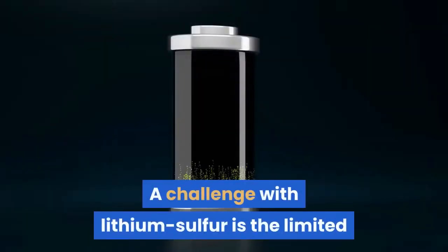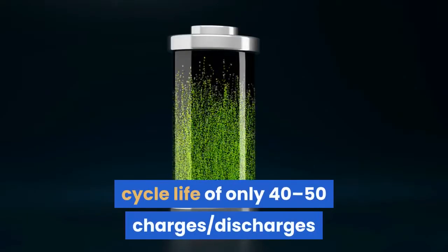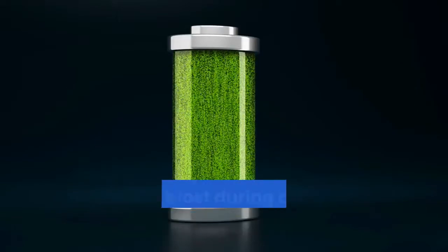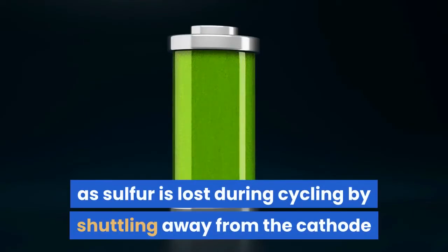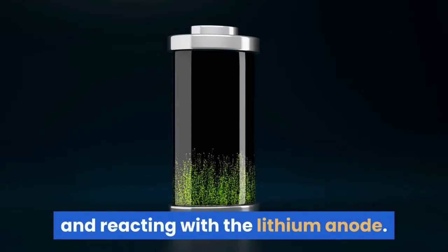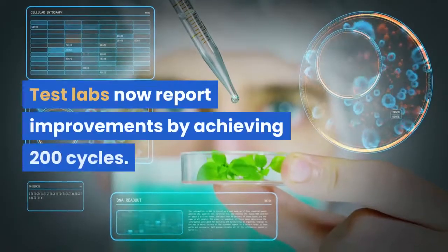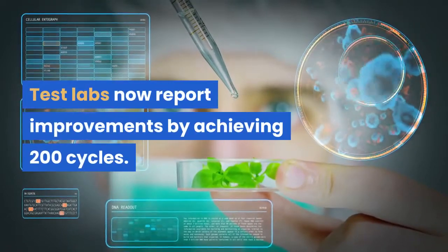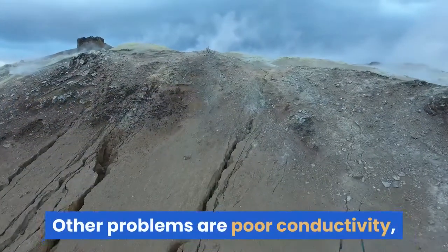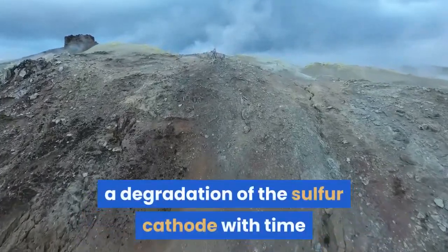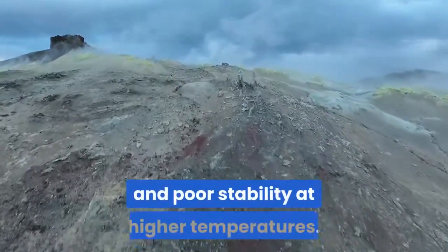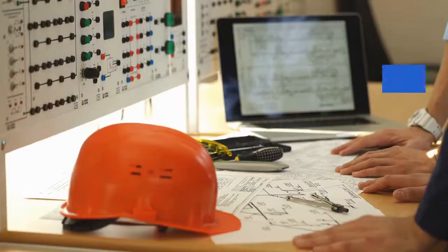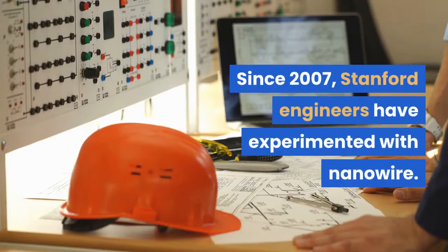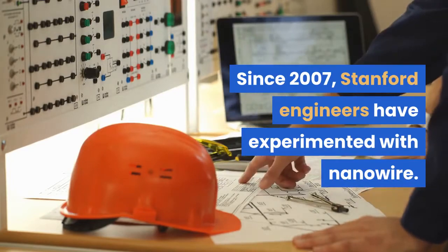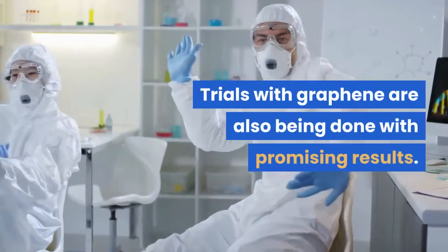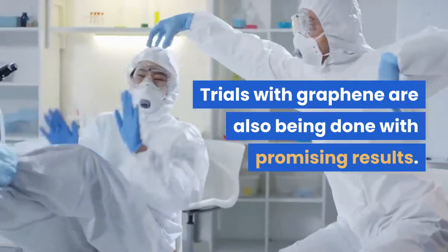A challenge with lithium-sulfur is the limited cycle life of only 40 to 50 discharges as sulfur is lost during cycling by shuttling away from the cathode and reacting with the lithium anode. Test labs now report improvements by achieving 200 cycles. Other problems are poor conductivity, a degradation of the sulfur cathode with time and poor stability at higher temperatures. Since 2007, Stanford engineers have experimented with nanowire. Trials with graphene are also being done with promising results.